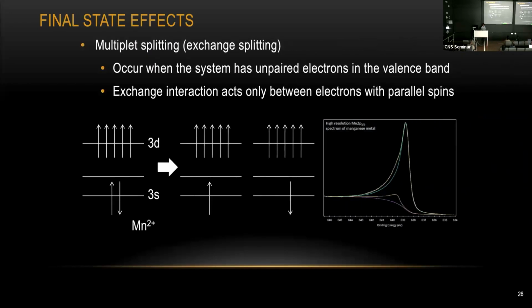The second final state effect is called multiplet splitting. What we're looking at here is a manganese 2+ sample. You can see we have five electrons filled in the 3d shell. If you're moving one single electron out from the 3s shell, now there is only one single electron in this shell, so it can either be spin up or spin down. That's why when you're looking at your data, you might see a double peak. That's due to the exchange splitting over here.